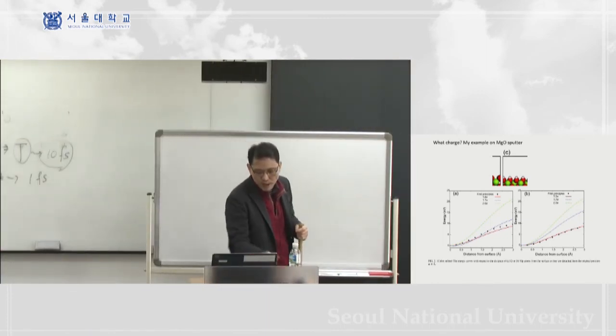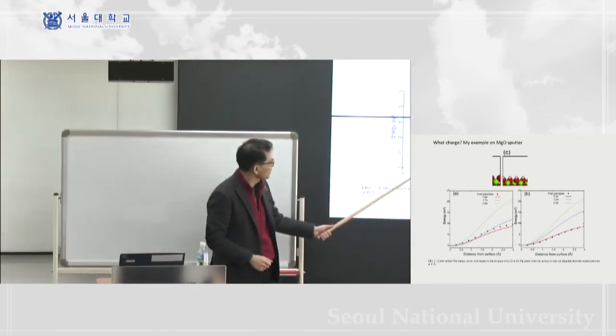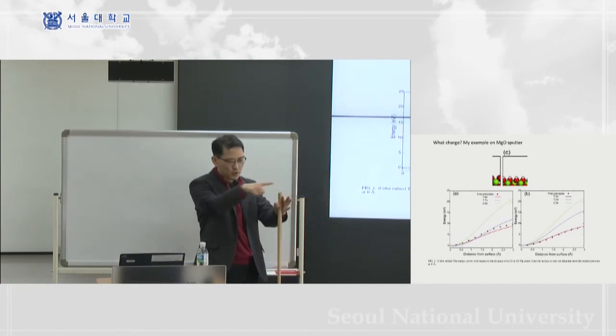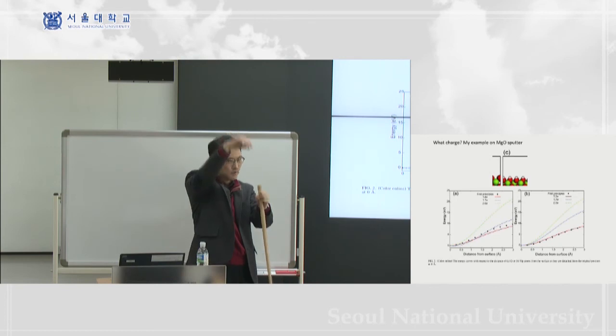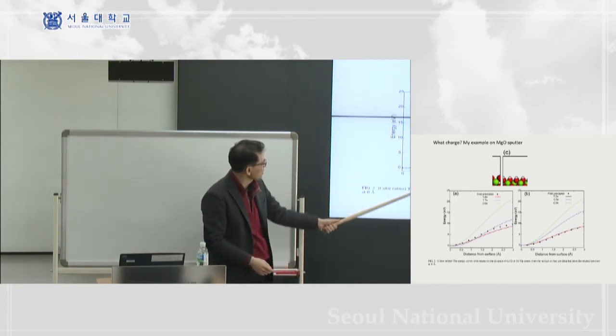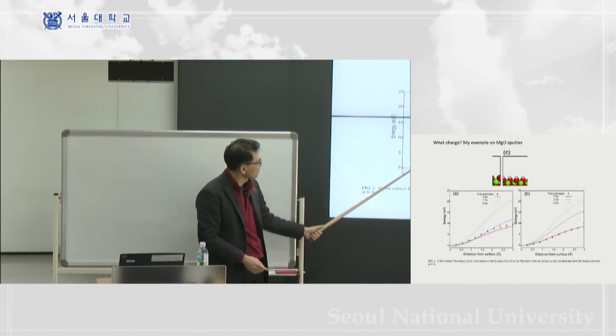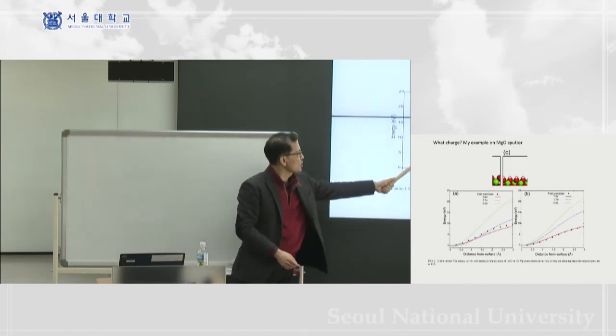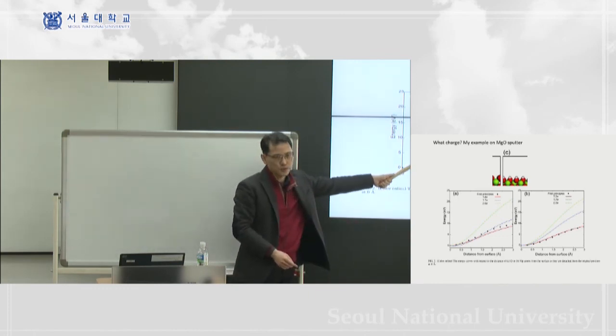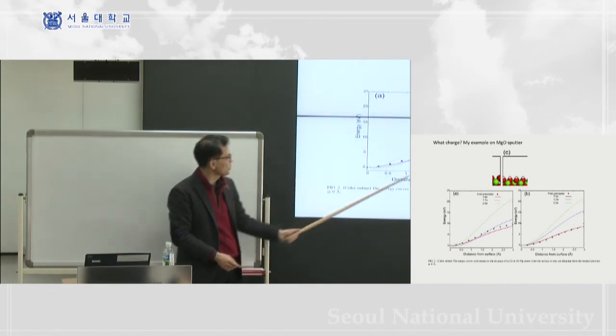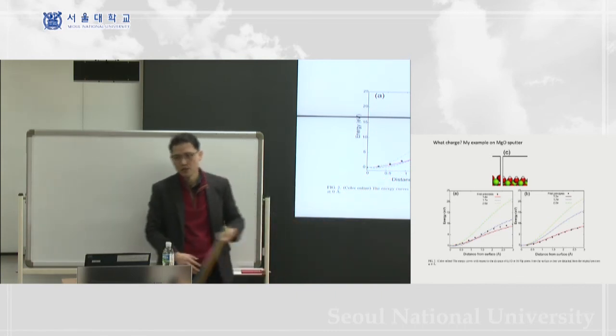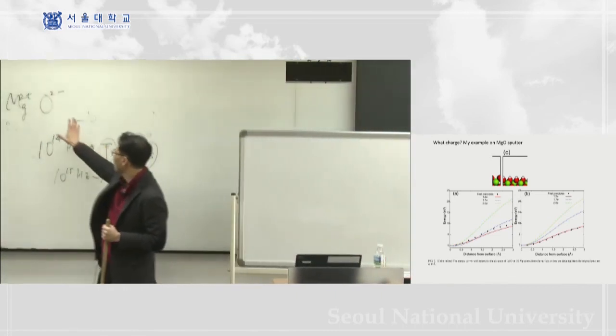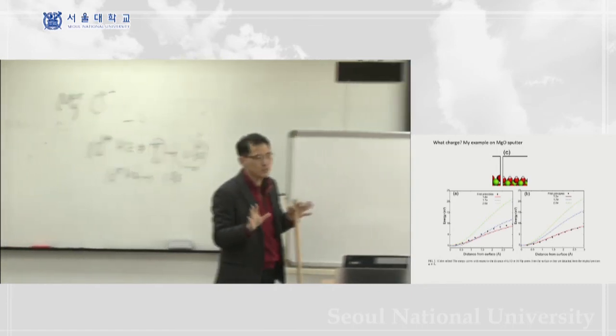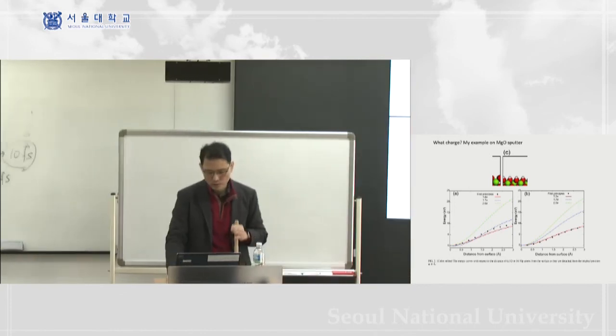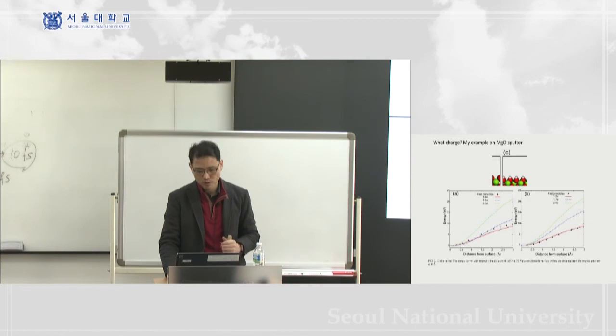However, if you use such a value as the charge in the ionic potential model, then this is the energy when you push out a magnesium or oxygen from the surface: the energy increases. This is what it describes here, and the accurate value from the quantum mechanics calculation is presented by the black dots. But if you use this fixed charge of 2, then it overestimates such an energy increase, and you have to decrease the charge down to 1.2 to obtain a reasonable description of the energy increase. This means that the chemical nominal charge is not the actual or precise value to put into this ionic model. So it should be tuned depending on the system or the situation.